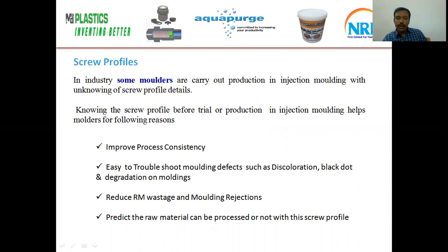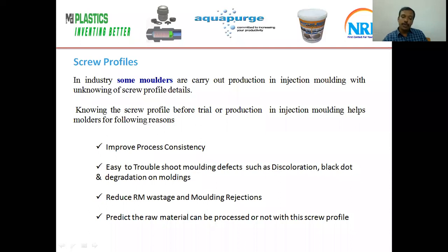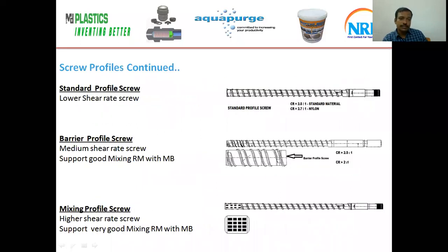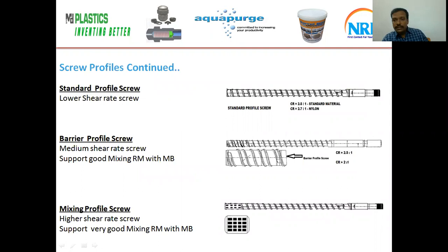See, if you mold raw material with master batch with the standard profile screw, it normally causes discoloration. So you need something like a barrier screw. It reduces RM wastage and molding rejection, and helps predict whether the raw material can be processed or not with the screw profile in the injection molding machine. See here, the schematic diagram shows the standard profile screw.